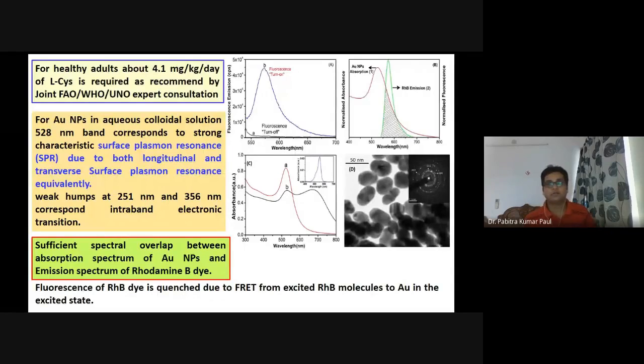Okay, thank you. You can see this fluorescence is almost completely turned off when you add the rhodamine B and gold nanoparticles to the solution, and when we add the L-Cysteine solution to the mixed solution, the fluorescence comes out. Initially the fluorescence is quenched by the FRET process from the dye molecules to the gold nanoparticles. Energy can be transferred to the gold nanoparticles because it has a large overlap, and this is fluorescence turn on. This recovery of the fluorescence is very much selective to this particular amino acid, and the amount of the recovery is linear to the concentration of the analyte L-Cysteine.